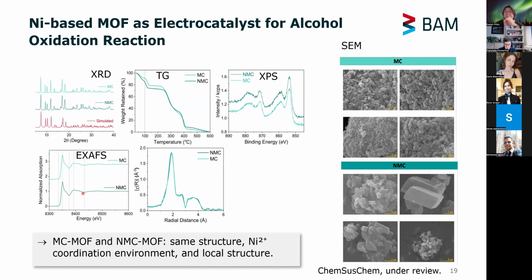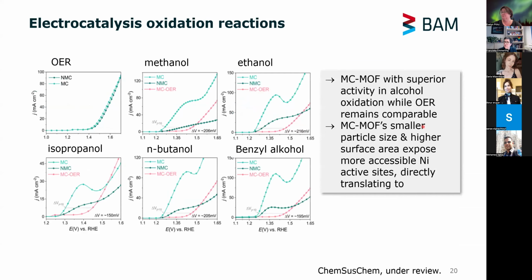from the local structure. But if you look a bit closer again here at the SEM images, you can see that the mechanochemically derived materials have again a smaller particle size, which in the end gives rise to a higher surface area. And then in the oxidation reactions, we can see here compared to the oxygen evolution reaction,